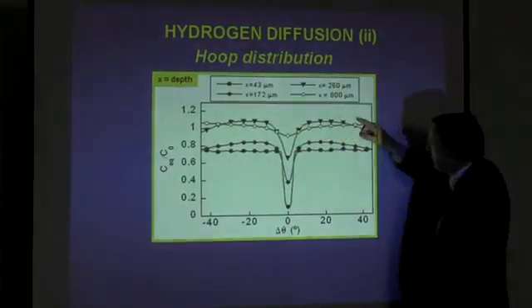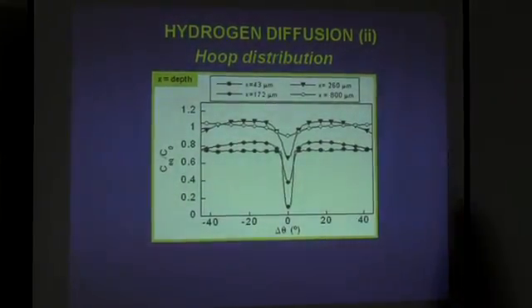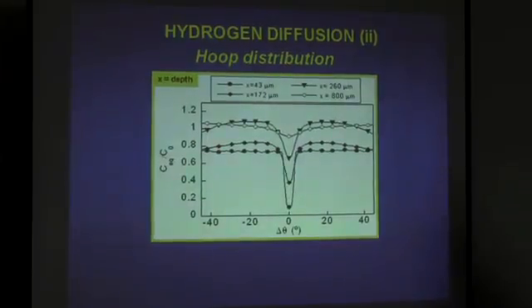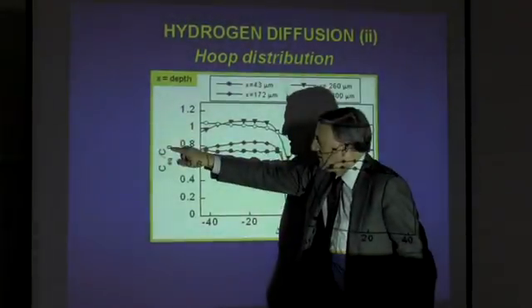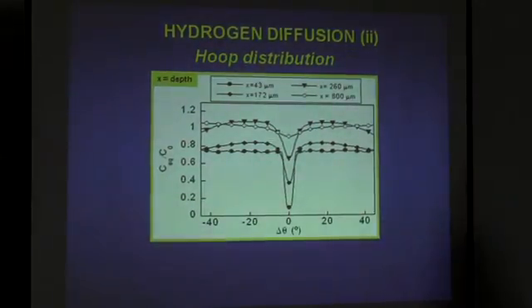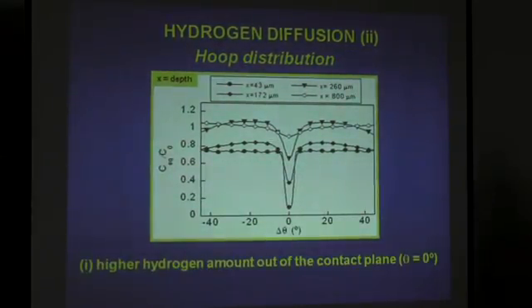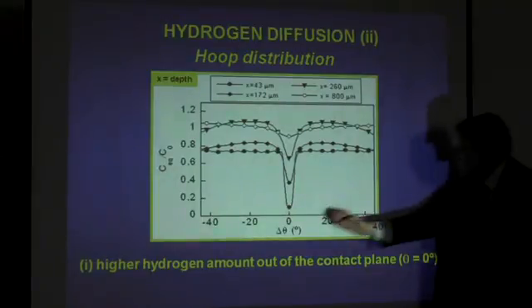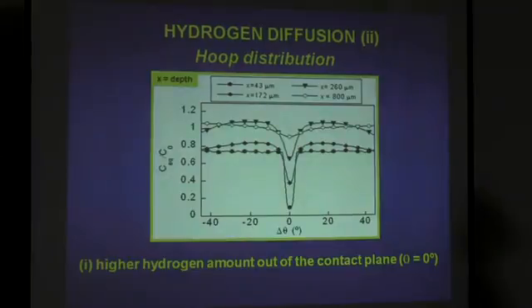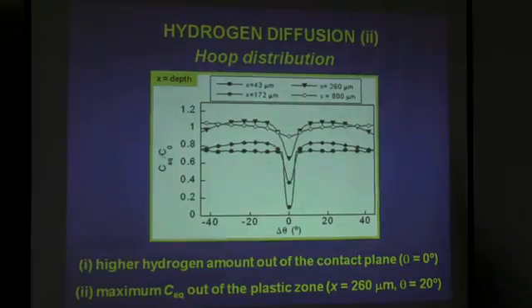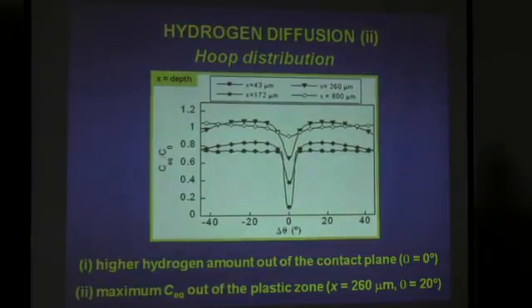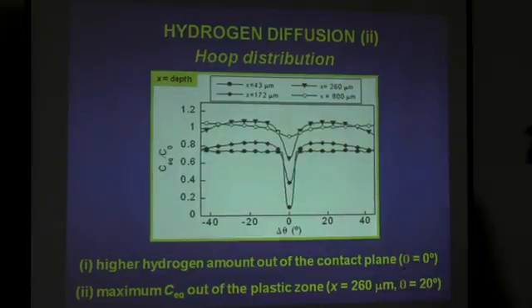With regard to the Hoop distribution, we have this shape with the local minimum and more or less uniform, with a maximum more or less at 20 degrees of concentration. Now this is hydrogen concentration normalized in dimensionless terms, the equilibrium hydrogen concentration for infinite time, divided by the concentration for the stress-free metal. This is the Hoop distribution. Higher hydrogen amount out of the contact plane, theta 0. Here we have the minimum. Then hydrogen is expelled from this heavily compressed contact area, and the maximum equilibrium is out of the plastic zone, more or less at a depth of 260 micrometers at an angle of 20 degrees.